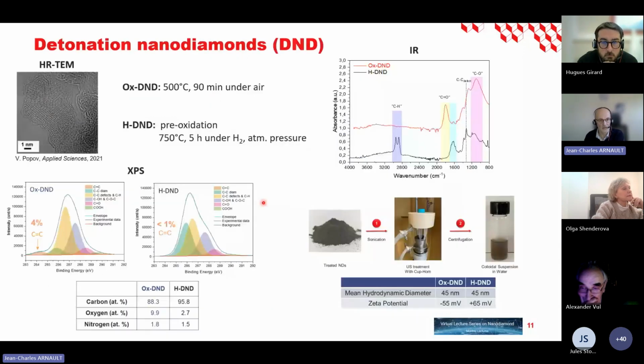So we will start with the detonation nanodiamonds, a well-known material, I would say, in the community. There are defects in the core, as you can see in this high-resolution TEM. You can tune the surface chemistry using gas phase treatment, and these are the fingerprints you can get in infrared and XPS experiments. Briefly, you see in the infrared that for the oxidized particles, you have all the features